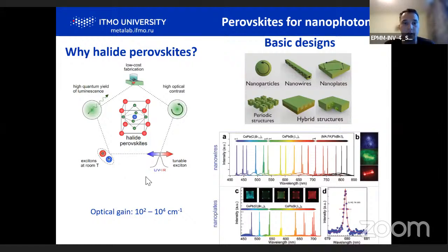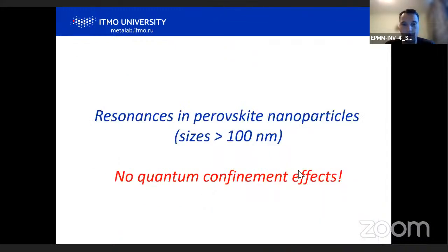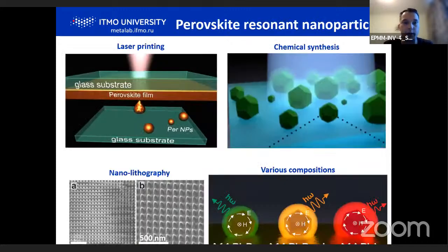And for nanophotonics, why are we interested in this material? Because it's low cost, it provides good optical contrast, it has tunable excitons at room temperature over the whole visible range, and it has high quantum yield and also high optical gain, which is important for lasing applications. I will start my talk by focusing on nanostructures and nanoparticles with sizes more than 100 nanometers. It means that we should forget about quantum confinement effects. We should think only about optical resonances.